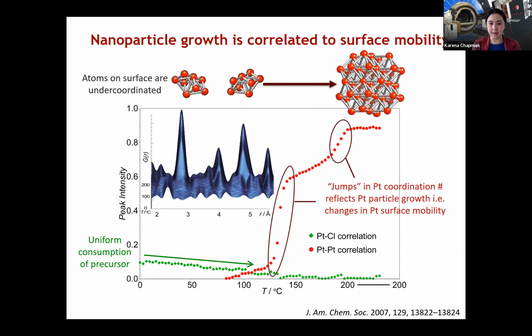The key thing we realized we could get out of this was seeing big jumps in the platinum coordination number, which corresponds to an increase in the concentration of platinum-platinum distances. But we haven't reduced any extra platinum—it's a fairly uniform reduction of the platinum.